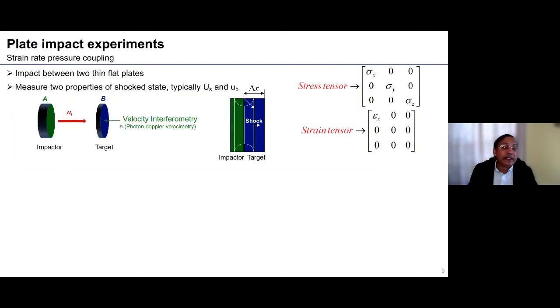This is a very well established technique, the shock wave technique, where you have an impactor impacting a target, and you generate a shock wave and uniaxial strain conditions. So there is only strain in the direction of the compression. And the stress, obviously, we have achieved close to a hydrodynamic state of stress.